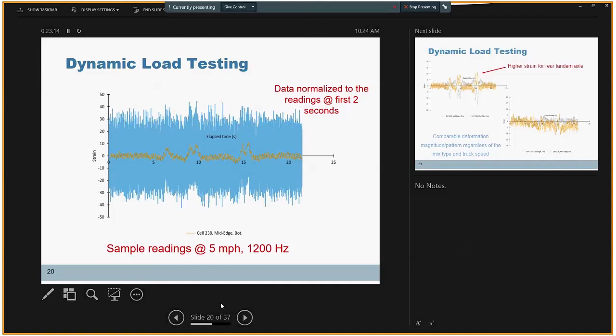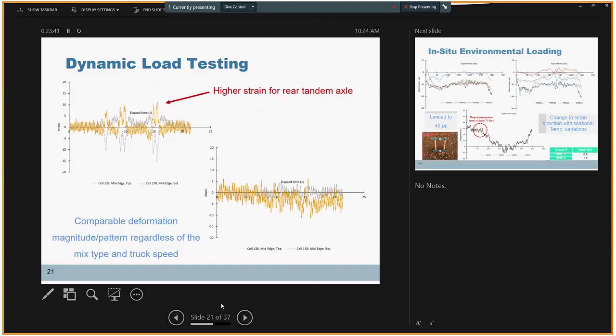Because of the high frequency and the nature of the test and the sensors used, there is some noise in the data. But in addition to recording the maximum and minimum strain values, we also decided to capture the trend line of the response of the pavements to controlled traffic loadings. So here's some typical data we got from these 2 experimental cells. Top graph, we have the data from the cell with lower cementitious material content, from sensors at top and bottom at mid edge of an instrumented panel.